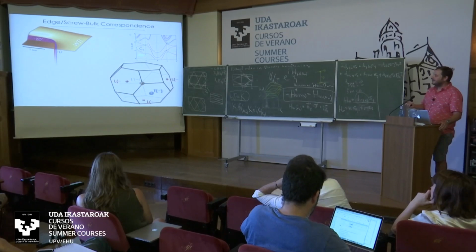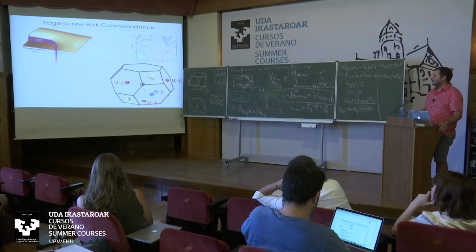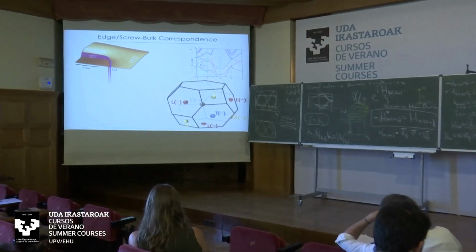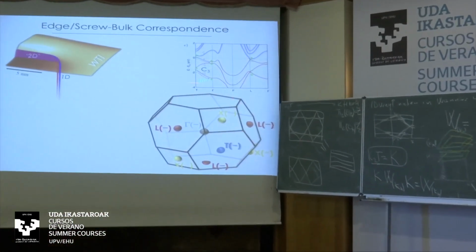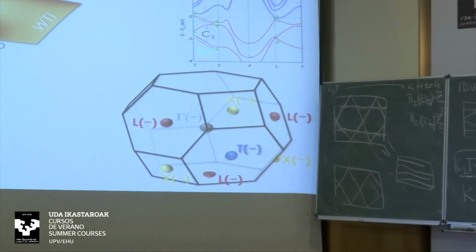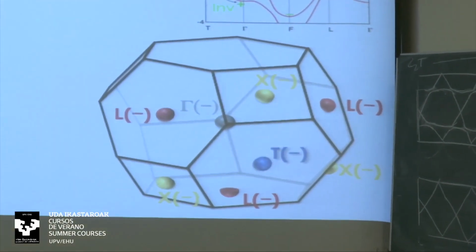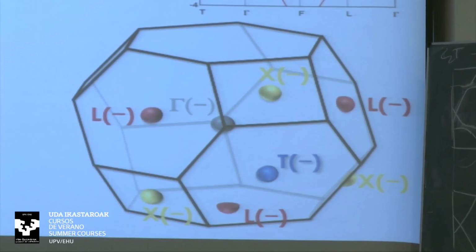So what could be the possible resolution is, again, this is the Brillouin zone of bismuth. These are the high symmetry points around the Brillouin zone. And because it is inversion symmetric, we can simply use the Fu-Kane formula to analyze the topological indices. So the strong topological index is just coming from the band inversion, the parities of all these 8 high symmetry points around the Brillouin zone, which if you multiply them add up to plus.